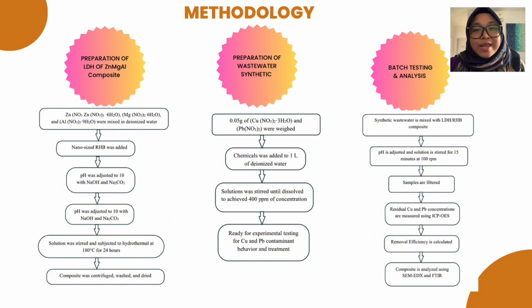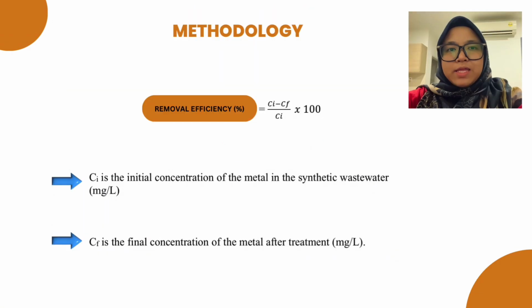effectiveness. And next, the batch testing involves adjusting the pH of the samples and analyzing the result by using the ICP-OES, SEM-EDX, and FTIR. This is the removal efficiency calculation of the heavy metals, copper and lead. This formula was used after we analyzed the sample by using ICP-OES.